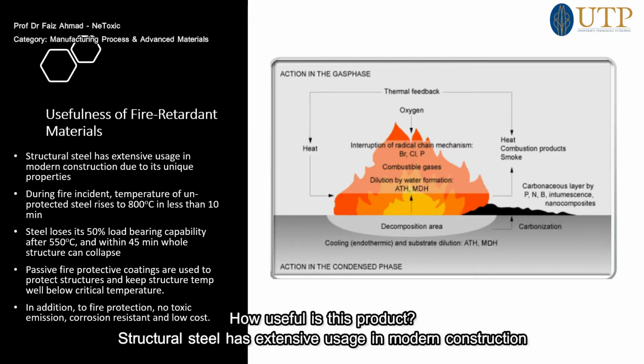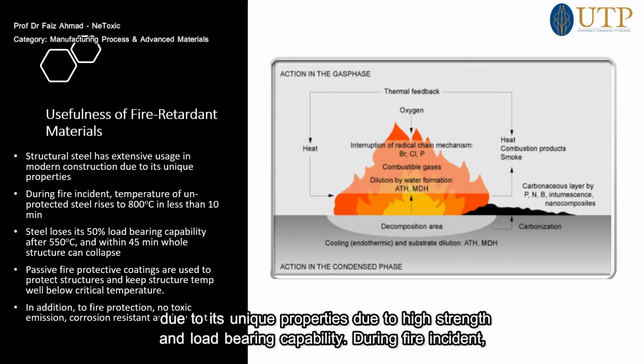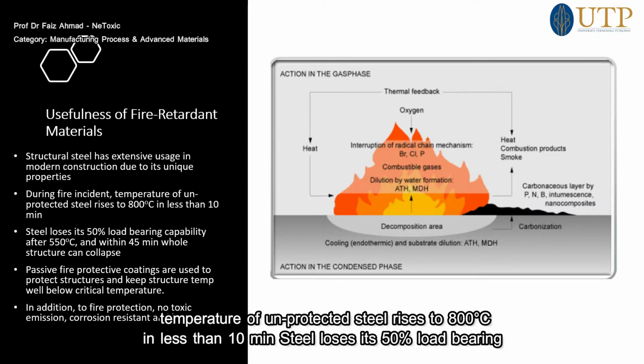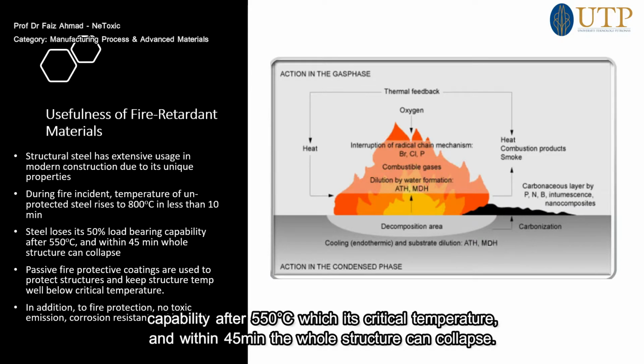How useful is this product? Structural steel is used extensively in the modern construction industry due to its unique properties of high strength and load-bearing capability. But during a fire, the temperature of unprotected steel rises to 800 degrees Celsius in less than 10 minutes, and steel loses 50% of its load-bearing capability after 550 degrees Celsius, which is a critical temperature. It takes 45 minutes, and the whole structure can collapse.